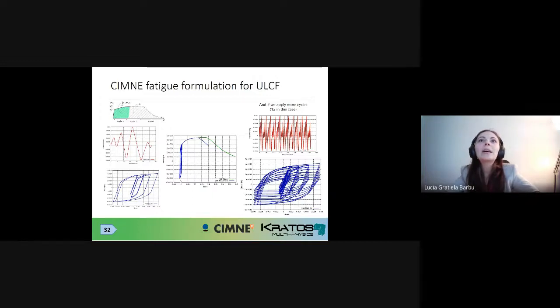Now, just to bear in mind that this ultra low cycle fatigue formulation, this specific constitutive law, is perfectly capable of capturing a random cyclic loading, and the effect that it has once you repeat it for a specific number of cycles, even with these very crazy hysteresis loops.